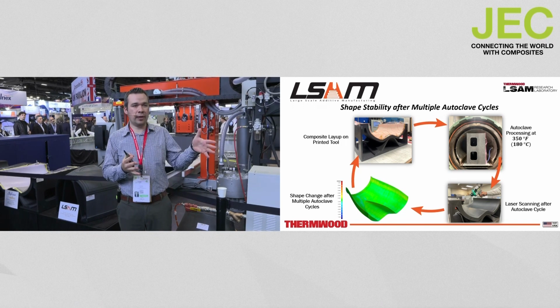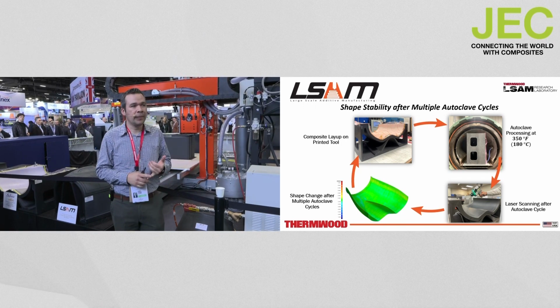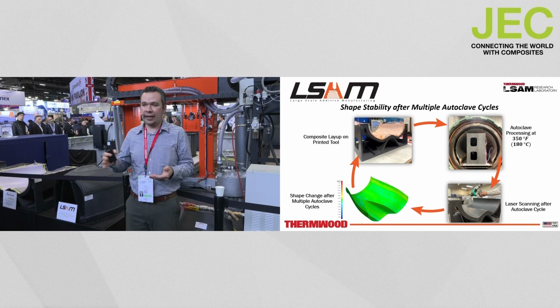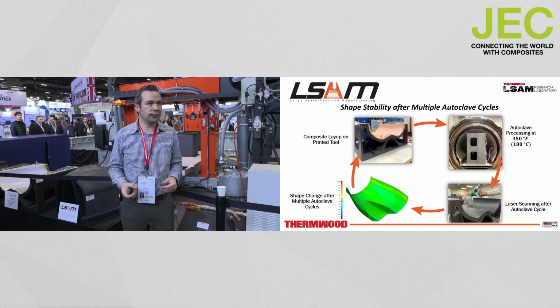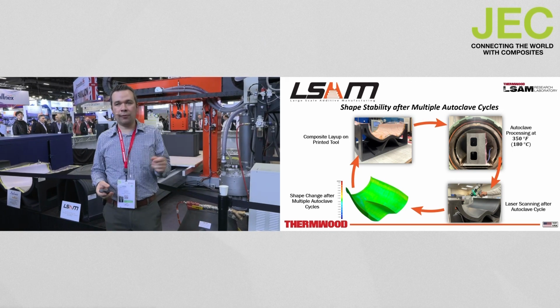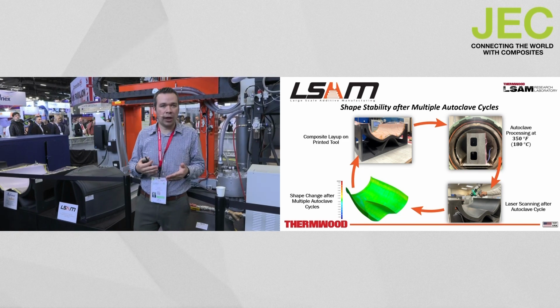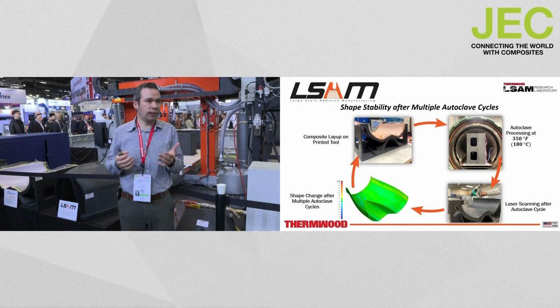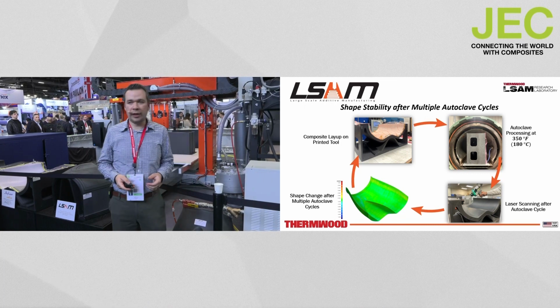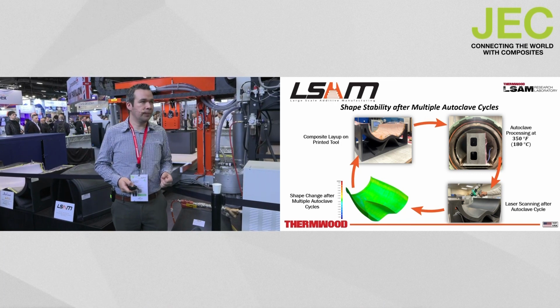It was cured in the autoclave at 180 Celsius, and then we laser scan and monitor the shape change over multiple cycles. So you can see on the bottom left corner a deviation plot after multiple cycles, and basically the shape and stability is really consistent throughout the multiple cycles of the tool.